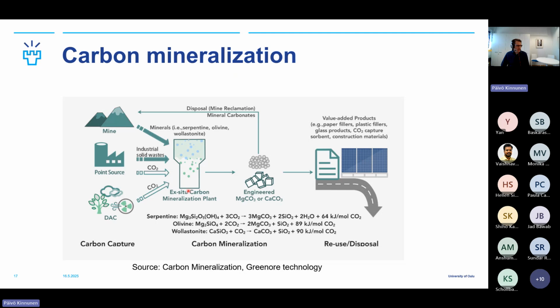Okay, so a bit of the chemistry here. Depending on which starting material you have, you have the carbon dioxide converting to carbonate and then reacting into different carbonates. So this is either magnesium carbonate or calcium carbonate, or a mixture of those. And depending on what temperature and pressure you do that at, you end up with either hydrated magnesium carbonates or with the unhydrated one, which is magnesite. And this magnesite is a thermodynamically stable end product and is favored because of that. But then you need higher temperatures and pressures in order to achieve that.